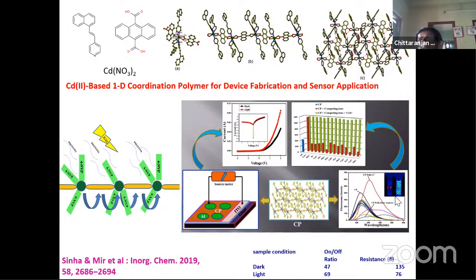Upon addition of different metal ions, only in the presence of chromium ion does it show sensitivity. That is, this coordination polymer is useful for two purposes, one for the conductivity measurement, the other for the sensing measurement. So not going into the detail of the sensing study, since our interaction is mainly on the conductivity.